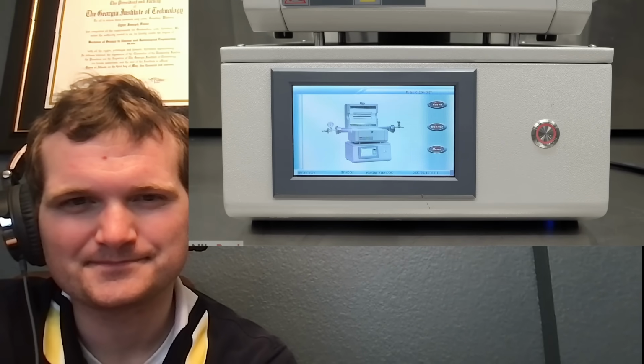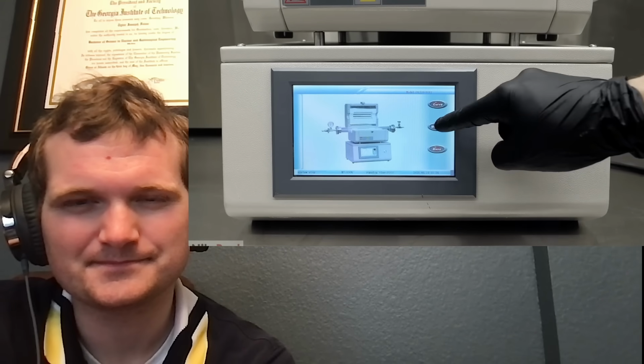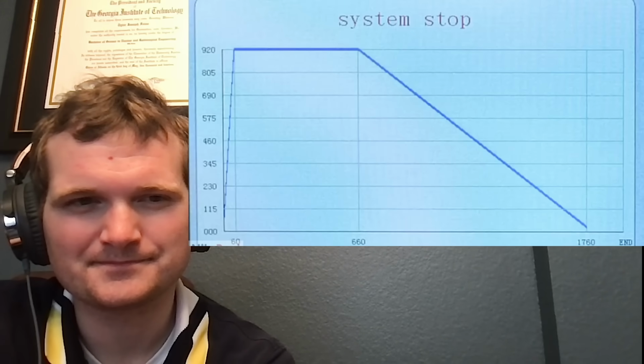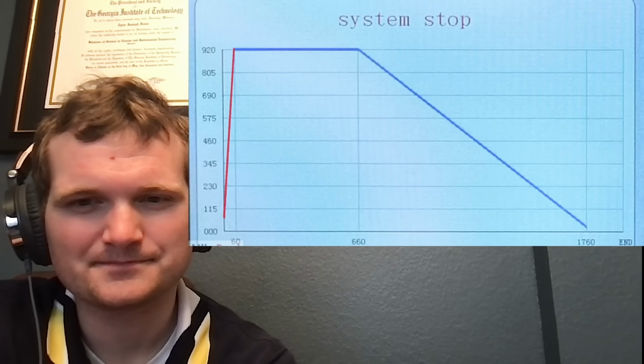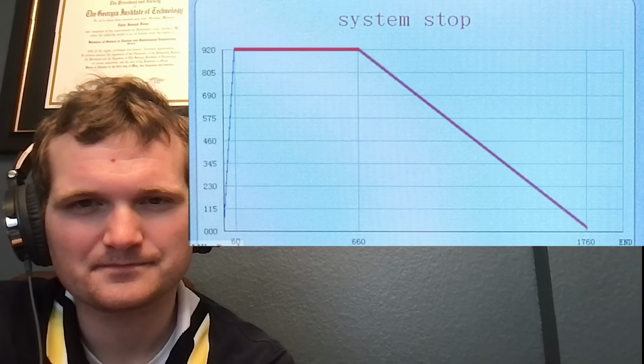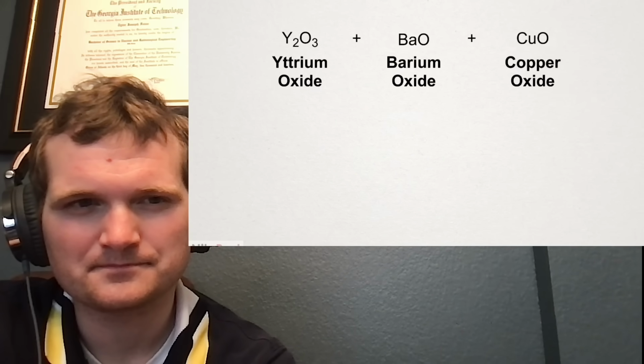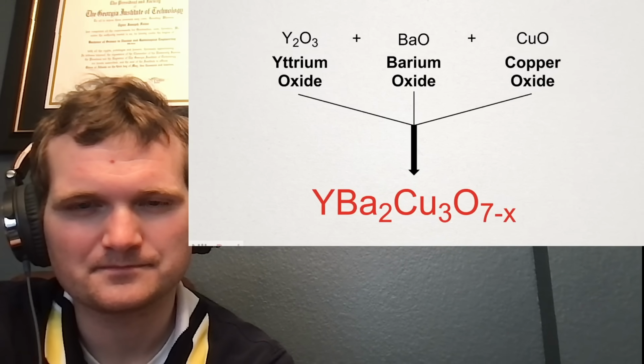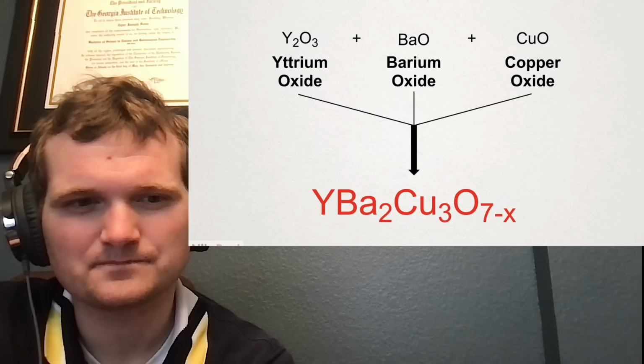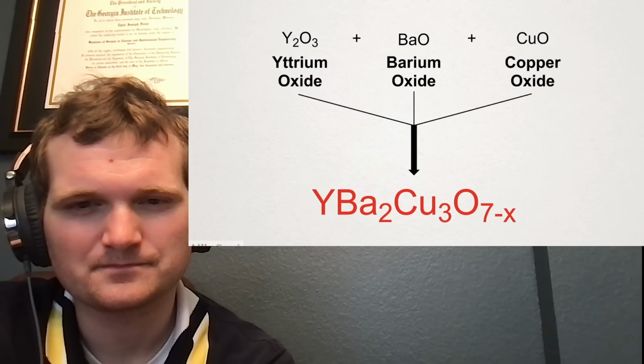After that, I turned on the furnace, and I checked the heating curve to make sure that it was the right one. I'd set this up beforehand, and it was pretty simple. Over an hour, it would be slowly heated to 920C, and then held there for 10 hours. After that, it would be slowly cooled at 50C an hour until it was room temperature. This whole process should cause the oxide powders to fuse together and form the YBCO. The slow cooling part would also let it crystallize, which was very important.